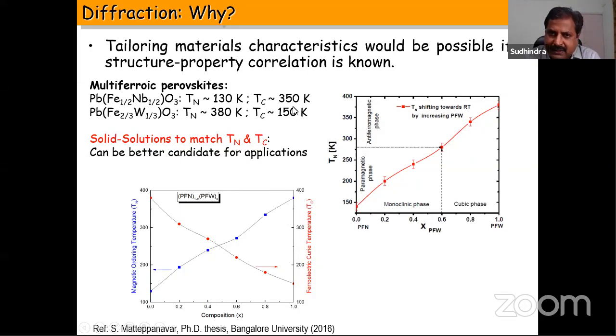So if you want a sample which should have an ordering temperature at room temperature and a Curie temperature also in the vicinity, what you do is make a solid solution of that. This is one of the theses which was done on our instrument in our center. You can see that at one of the concentrations, you have a TC which is close to room temperature, and also the TN which is in a comparable range. If you know the structural properties, you see that at this concentration, there is a crossover from monoclinic phase to the cubic phase, or vice versa, whichever way you look at it.